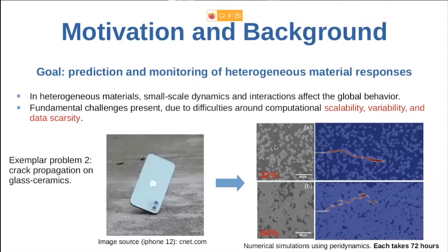The glass ceramics is better than the conventional glass material because it has superior material properties, such as better fracture toughness. Basically, your iPhone is less likely to have a totally broken screen. However, as you can see here, when you have a different fraction of the crystal, or a different microstructure, the crack pattern is totally different.